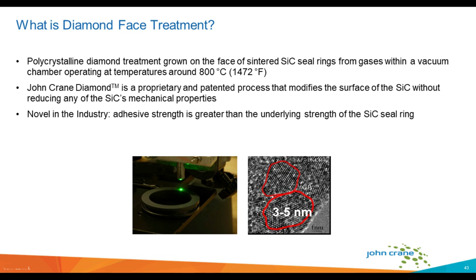The diamond is grown directly on the surface of that ring using something called a CVD process, which is a chemical vapor deposition process for the application. So utilizing gases within a vacuum chamber and some very high temperatures, around 800 degrees C, to form this diamond growth on the surface of that seal face. With this process there is a very uniform growth rate on the surface of the seal ring, so overall there's no real impact in terms of the mechanical properties of the seal ring itself.